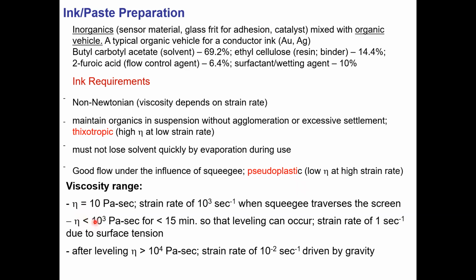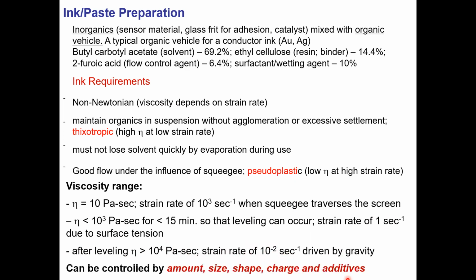Then after printing is done, you want the viscosity of the ink to go up in this range for a small amount of time where you get the leveling. Remember, there has to be lateral movement to connect the dots, isolated dots that you typically get after printing. And the strain rate there is controlled by the surface tension. The film is still wet, and the strain rate is of the order of 1 hertz. And after leveling, you want the viscosity to go up so that you don't get bleeding, so flowing all over the place. The strain rate there is under gravitational force, a very low strain rate. So this gives you a ballpark range of viscosity that you need to target.